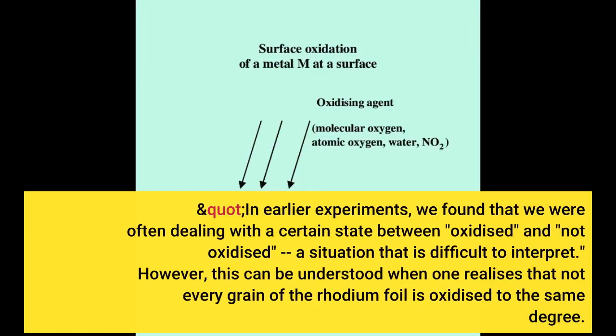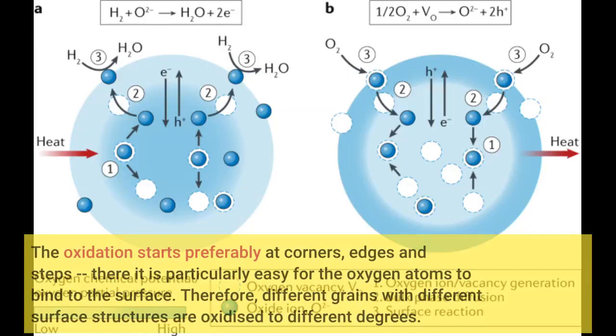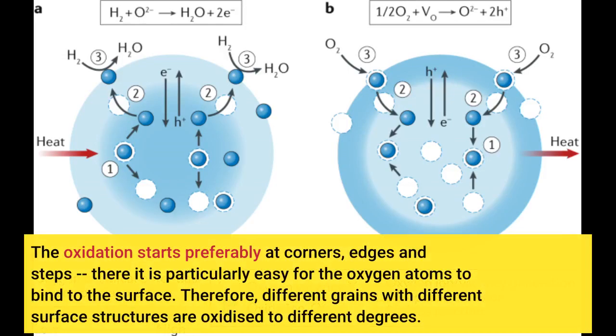However, this can be understood when one realizes that not every grain of the rhodium foil is oxidized to the same degree. The oxidation starts preferably at corners, edges and steps. There it is particularly easy for the oxygen atoms to bind to the surface. Therefore, different grains with different surface structures are oxidized to different degrees.